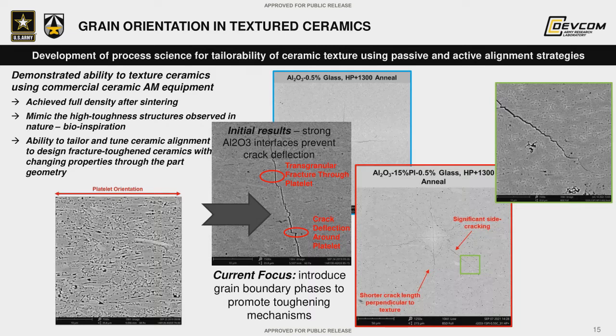However, there are also some limitations with this. In our initial results, we had strong alumina interfaces, which prevented the cracks from actually seeing this microstructural texture. So instead of diverting around the platelets in the microstructure, cracks would just go straight through that. So our current focus is twofold.